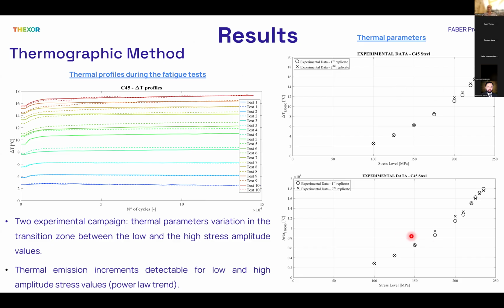The thermal parameters evolution as a function of the stress amplitude are reported on the right side. The thermal parameters adopted in this research activity were the thermal increment and the thermal area. The circle symbol refers to the first experimental campaign, while the X symbol refers to the second experimental campaign. As you can see, there are differences in the thermal parameters in the transition zone.